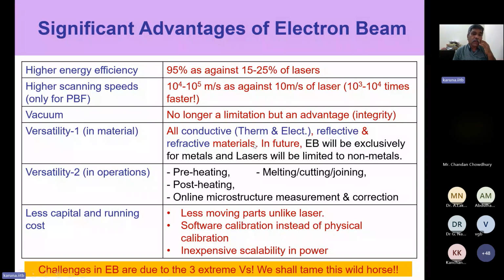So electron beam very comfortably handles all types of metals, whether the metal is a poor conductor or good conductor, reflective, refractive, it handles very well. Whereas with laser, for highly conductive materials like aluminum, silver, gold, copper, it struggles, because these materials reflect most of the laser energy, since it is optical energy, and very little goes into the part. Whereas electron beam comfortably handles copper, gold, every kind of material, even refractive material like tantalum, very complicated materials, with greater ease. That is in terms of material.